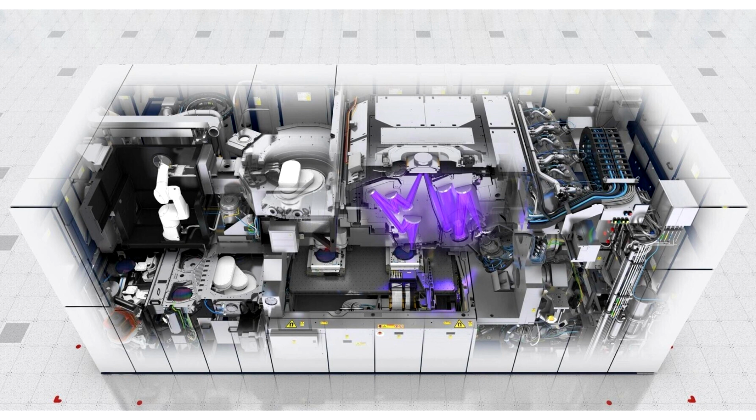This means that without EUV, SMIC has to look into alternatives like SAQP to increase the density of its nodes and, as a result, include more complications and possibly lower yields. As an example, Intel tried to use SAQP in its first 10 nanometers nodes to reduce reliance on EUV, which resulted in a series of delays and complications, eventually pushing Intel into EUV.